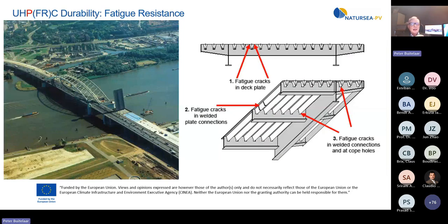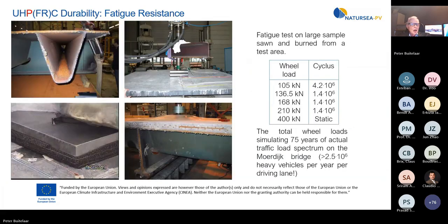The reduction of fatigue-related problems of orthotropic steel decks by applying a thin bonded hybrid reinforced UHPC, done early on container ships and a dry dock, has been very successful. This UHPC application is now used worldwide as a rehabilitation method. Fatigue tests on cracked and uncracked orthotropic steel decks with the thin bonded hybrid reinforced UHPC have been executed and have shown impressive service life extension up to 75 years.